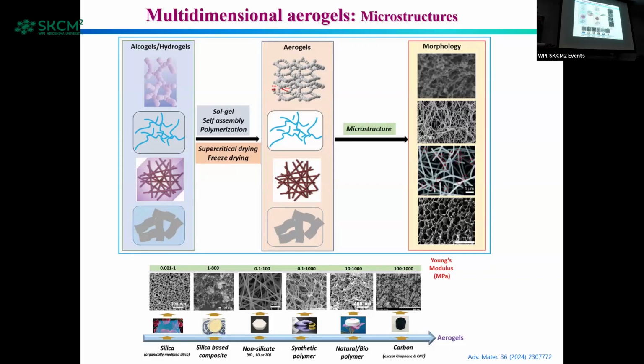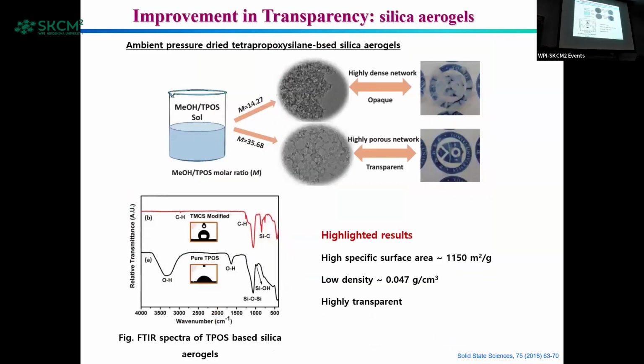So different kinds of aerogels we worked on. We prepared carbon-based aerogels, polymer-based aerogels, and transparent silica-based aerogels with higher modulus. And we achieved a modulus of around 1 gigapascal for carbon aerogels, what we prepared till now. Generally, I will just briefly discuss my work, what we did.